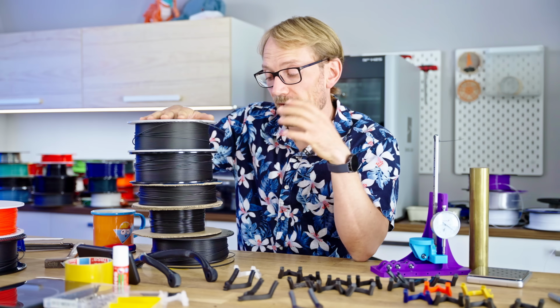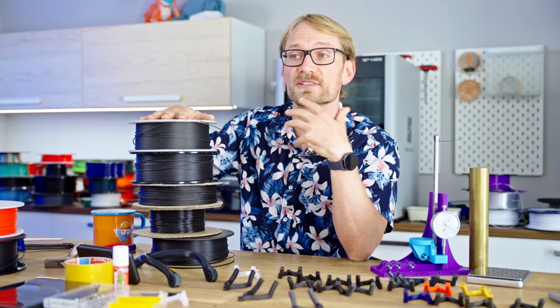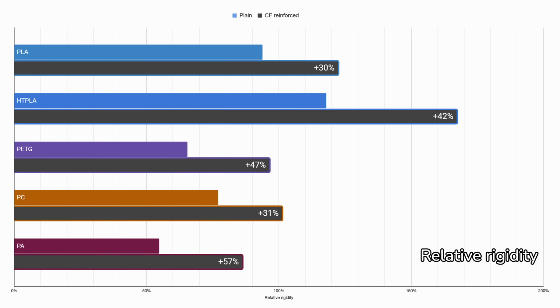I've also looked at how the carbon fiber changes the stiffness of these parts, because I do have 5 different filaments that I have in a plain and a carbon fiber version. And on average, it improves the rigidity of these parts by about 40%, which is pretty good. The materials that are less rigid by themselves profit more, versus something like a PLA, which already is quite stiff by itself, that profits less.